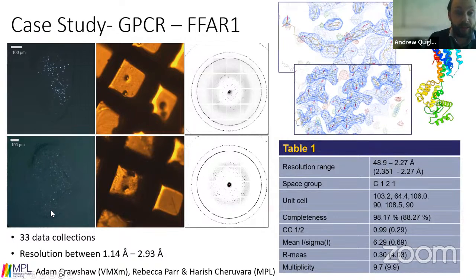The size of these crystals, the biggest ones are about 5 microns, the smallest being about a micron in size. In the next set of images, you can see the crystals on the grid, these little flecks within the squares. And then, just example patterns from the beamline. So from these 2 drops, we were able to mount a whole series of crystals and carried out 33 data collections from these two sets of cryo-EM grids. The crystals were diffracting from between 1.1 and 2.9 angstroms across the 2 drops.